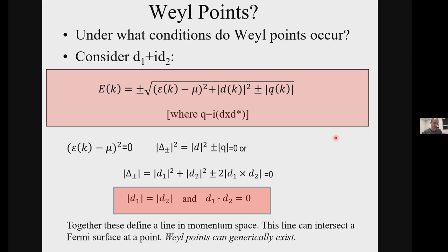Daniel, a short question from Eun-Ah: is this material quasi-2D or 3D? So the pocket that was seen is 3D, meaning it looks like a closed pocket. However, band structure calculations, LDA plus U, suggest there are also quasi-2D Fermi surfaces, and so it's a mixture. That's also part of the debate. Thanks. Okay, so let me come back to this.